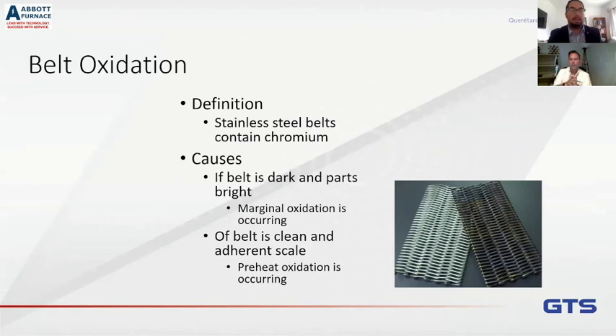If the belt is clean and you have this really adherent oxide, typically that's what's happening in the front of the furnace, and it's oxidizing so much that you don't have enough hydrogen in the furnace to clean it. And if it's very adherent, it's typically happening in the front. Correct. Okay, so we're talking about discoloration, oxidation, flashing.